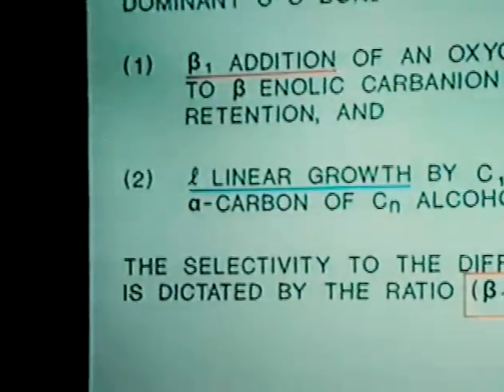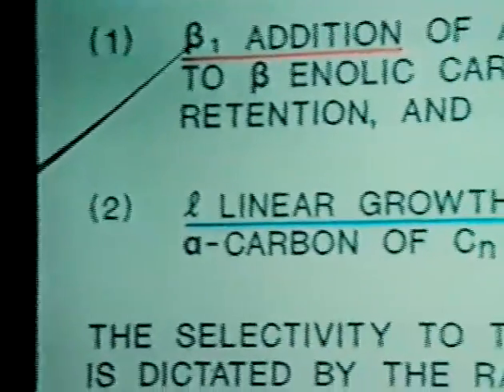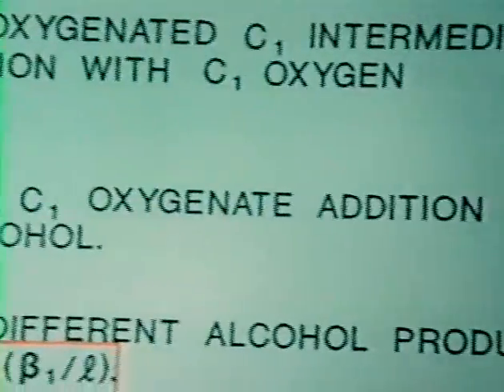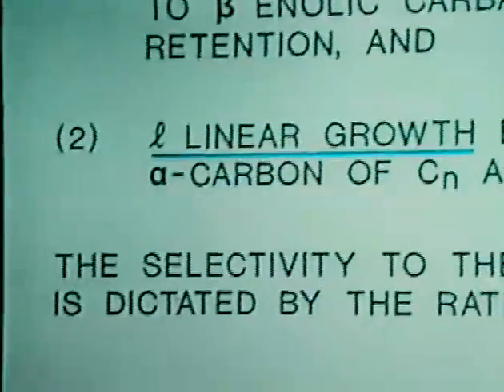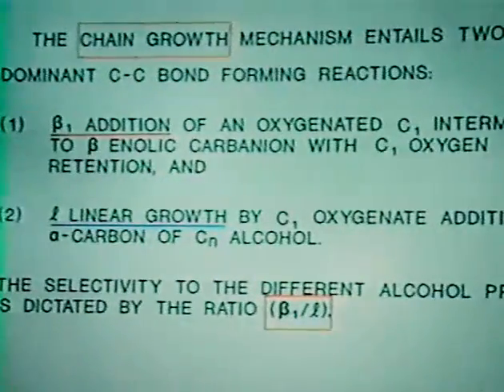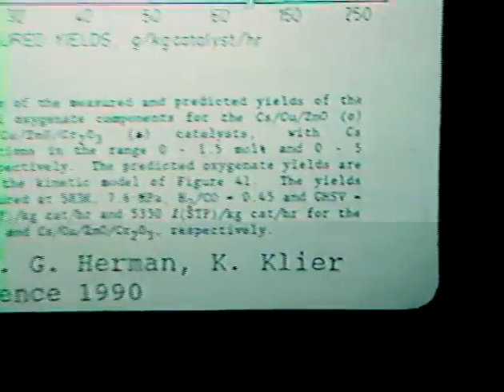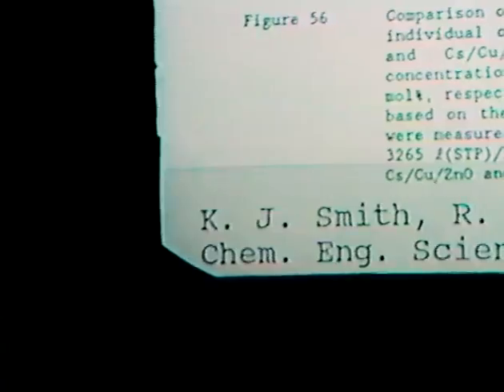Now, the effect of cesium is that it makes this reaction extremely efficient. Now imagine you have ethanol that has the beta carbon that goes very efficiently to linear propanol. So you expect a product composition in which ethanol will be at minimum. And then you will get linear propanol, and next will be 2-methyl-1-propanol, otherwise known as isobutanol. When all of this is worked out in mathematical terms, you invite Kevin Smith to do this for you. He produces an engineering model, and these chemical mechanisms are embedded into an engineering model which has 5 kinetic constants and predicts 25 different products.